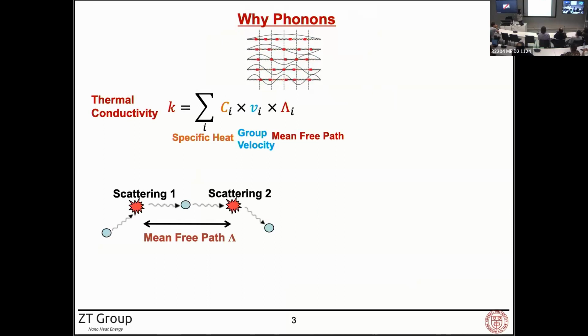Because mean free path is the product of group velocity and lifetime, we can also write this equation in terms of lifetime. I want to draw your attention to this summation sign here. The thermal conductivity essentially is the accumulative contribution from different phonon modes. So instead of just looking at one single number K, we want to dive deeper to get the microscopic picture of how different phonon modes contribute to the thermal conductivity.